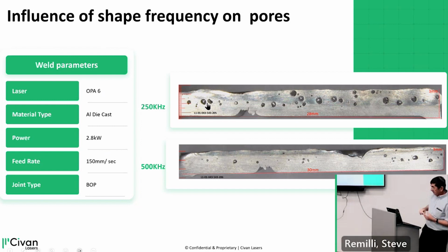And what's important to note here, the point of this slide is to show the difference between 250 kilohertz and 500 kilohertz. Because when we come and introduce this to people, they say, the molten metal, these are big things. They don't move so fast. I can do it with a galvo scanner. You know, IPG gives galvo scanners, and you can do it at a few kilohertz. Nothing moves faster than a few kilohertz, but it's wrong.